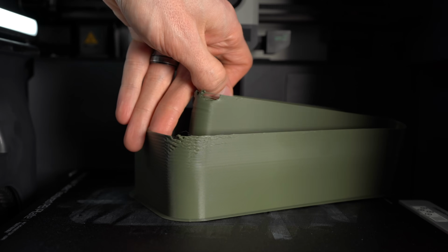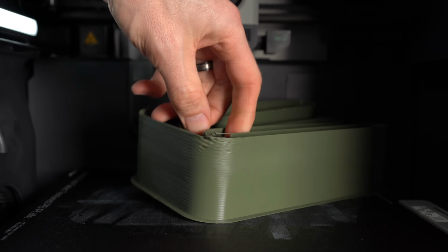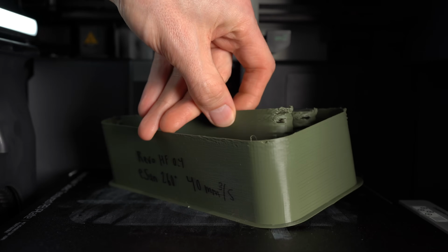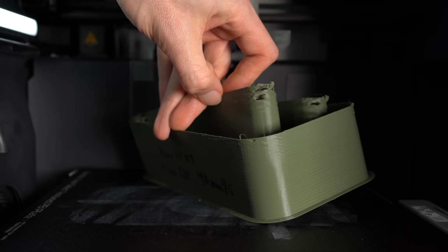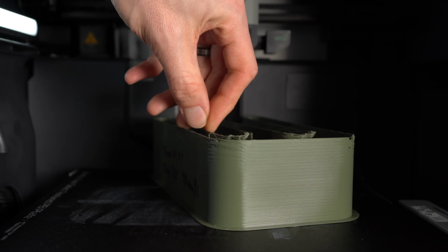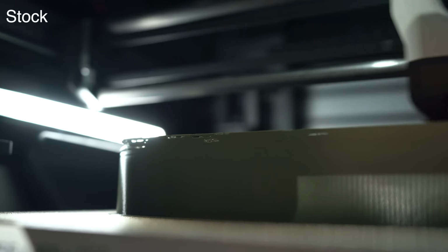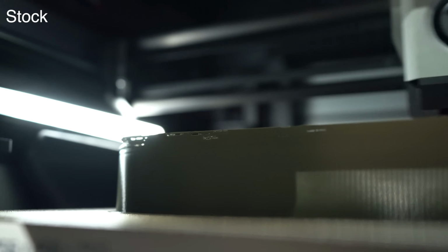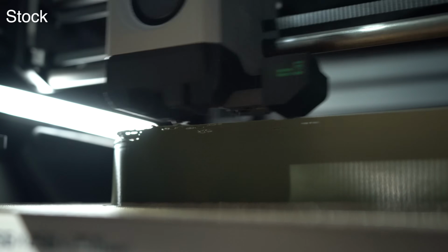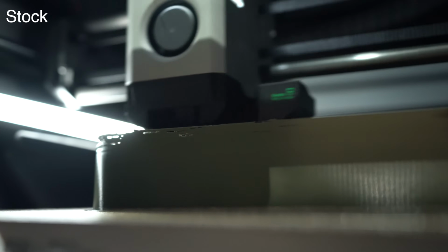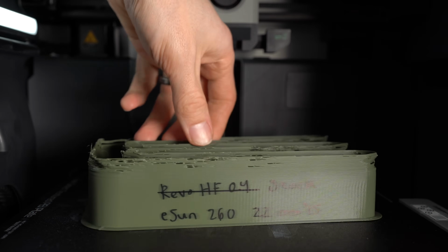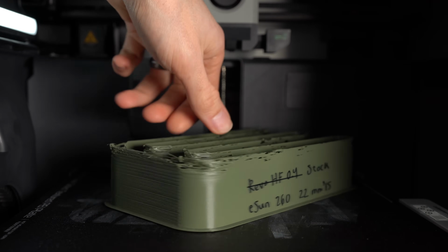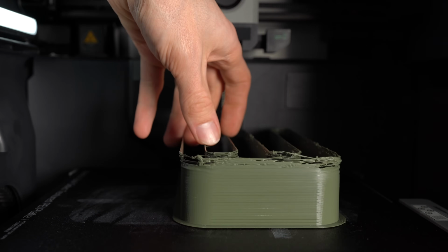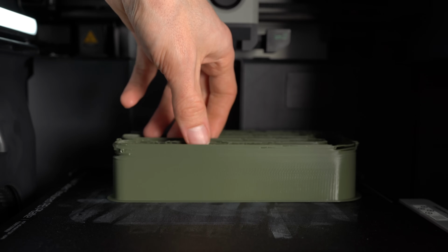However, as we get closer to the top, the inner edges started to curl in, which seems to indicate insufficient cooling. And at the corners, we have gaps, which I believe is because the nozzle pressure can't be maintained. So can it print at 40 cubic millimeters per second? Sort of. But do we even need this much flow? Actually, no. I'll tell you a little later on why, for practical purposes, any more than about 25 cubic millimeters per second has no tangible benefit.